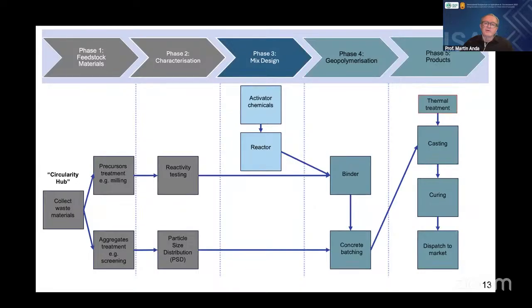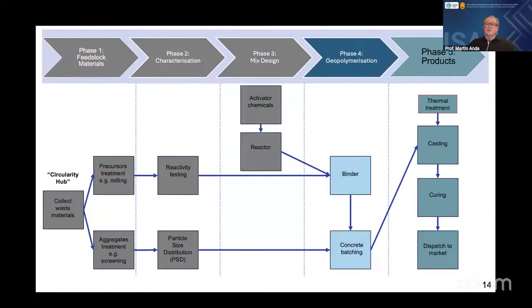And then along with the precursor material, we go into phase 4, which is the geopolymerization, where we want to prepare the binder from the precursor and the activator chemicals. And then we go into the concrete batching plant with the aggregates. And there may need to be a small amount of water added just to get the ratios right and the workability right, but not in the same way that you add water to a normal concrete batching plant. You have to be very careful, in fact, that you don't add too much water, and that's a small amount usually in the mix design.